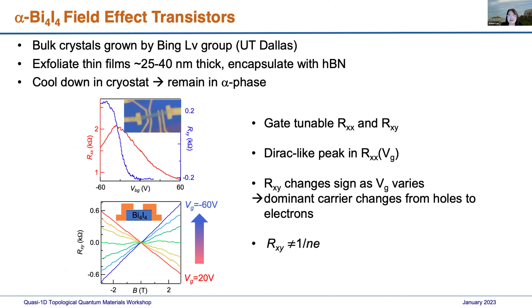The samples we make are between 25 to 40 nanometers thick. Since this material is sensitive to air, we encapsulate them with hexagonal boron nitride, and the exfoliation and encapsulation are done in a glove box. We then cool the sample down adiabatically in a cryostat — we did not do anything special like quenching — so they should remain in the alpha phase.